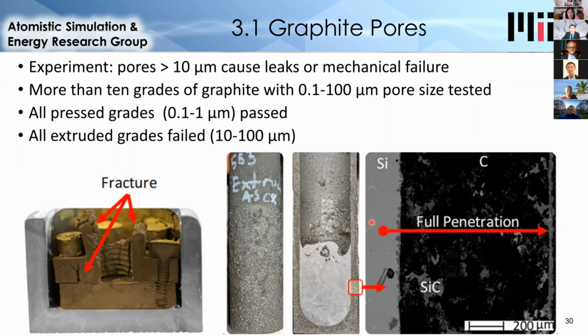The figure on the right shows a different scenario where a different grade of graphite resulted in leaking, but no mechanical failure. And so in the SEM image shown on the far right, we can see silicon, the graphite wall, and then on the far side of the graphite wall, we see this gray material, which is silicon again, which shows that silicon traveled all the way through the wall. You could also see silicon dripped on the surface beneath this tank after the experiment. And so this showed that, in fact, pores greater than 10 microns definitely cannot contain silicon.